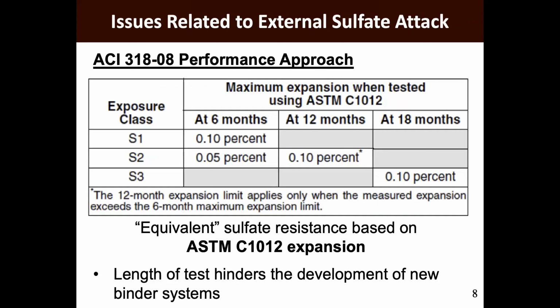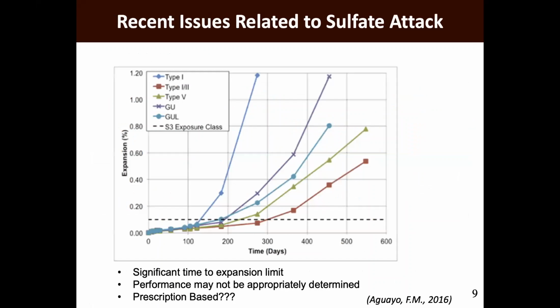And then again, if you look at 318 or 201, there's this performance-based method in which you either test at 6, 12, 18 months, and as long as you meet a certain expansion criteria, then you can meet performance that way as well. However, the length of the test really is a drawback, right? So we really don't want to look at a length of 6 or even 8, especially 18 months, in order to do this particular type of test.